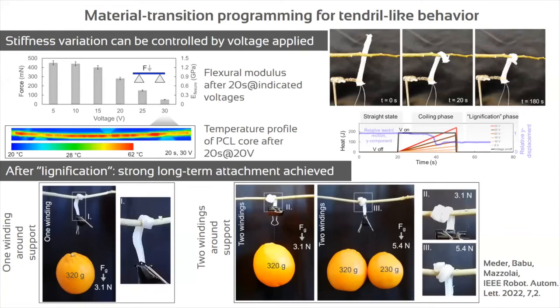But what we can achieve is a difference in the stiffness of this soft arm by playing with the PCL core inside the structure. And so we can use it for anchoring, and to maintain the attachment of a robot or different devices. In this case, the process is not reversible like in the natural tendril.